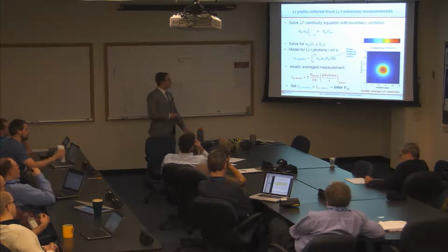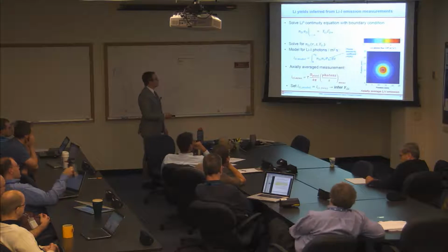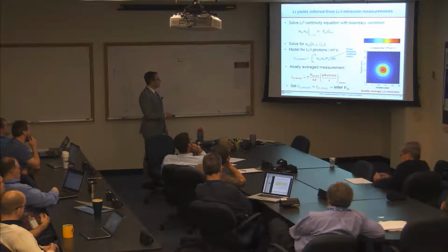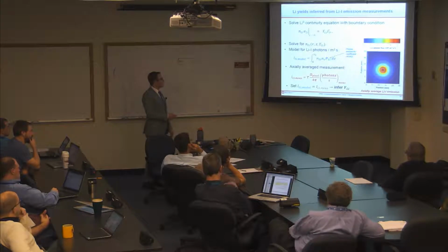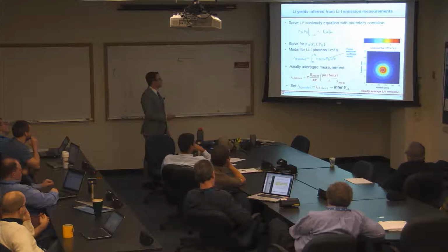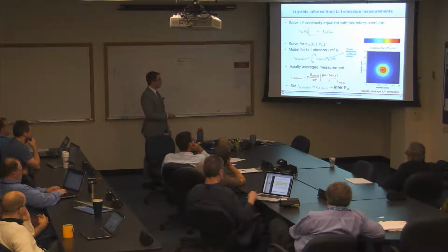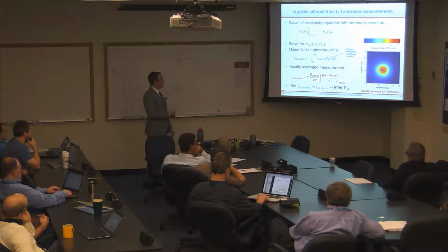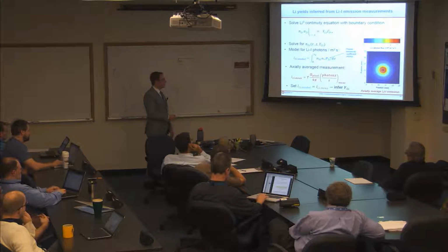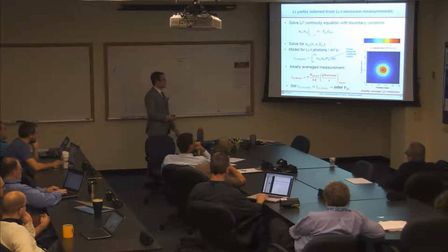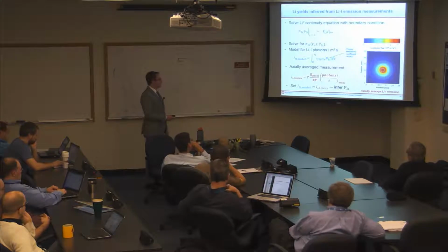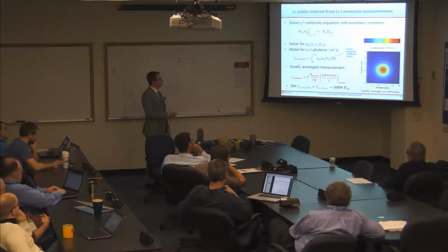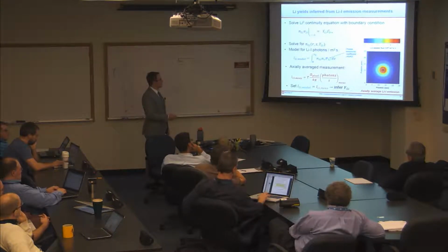So now that you have the lithium densities, how do you measure the erosion yield? Well, you solve this continuity equation with the simple boundary condition that the flux of lithium from the surface is equal to the erosion yield times the incident ion flux. That's basically just defining what Y is. And then you solve for the lithium density. Your model for what the lithium-1 photon flux should be is N lithium times Ne times P, which is the photon emissivity coefficient, also a rate coefficient in centimeter cubed per second, that comes from the ADAS database. And so you have a model for how much lithium emission you expect as a function of Y. Your only free parameter now is Y. And then you compare that to the measurement of the lithium-1 photon flux.